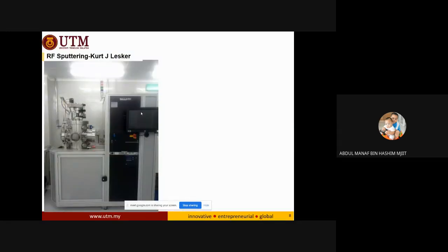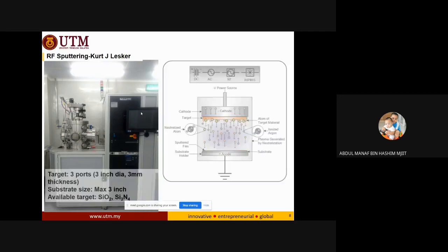Okay, also we have RF sputtering. The system has 3 ports, so we can put 3 targets. The specification of the target is 3 inches in diameter and 3 millimeters thick. The maximum sample size is also up to 3 inches. Currently we have silicon dioxide and also silicon nitride targets. If you have any other material to be deposited, you can bring your own.